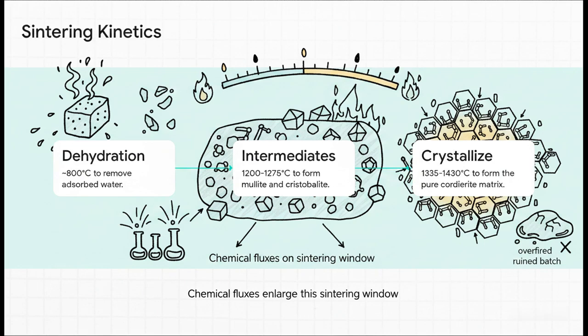Cordierite has an extremely narrow thermal window to get this right. The sintering kinetics happen in 3 strict steps. First, dehydration around 800 degrees Celsius to essentially bake out all the structural water. Second, between 1200 and 1275 degrees, intermediate phases like mullite and cristobalite form. And finally, the true magic happens between 1335 and 1430 degrees Celsius, bulk crystallization into the pure cordierite matrix.